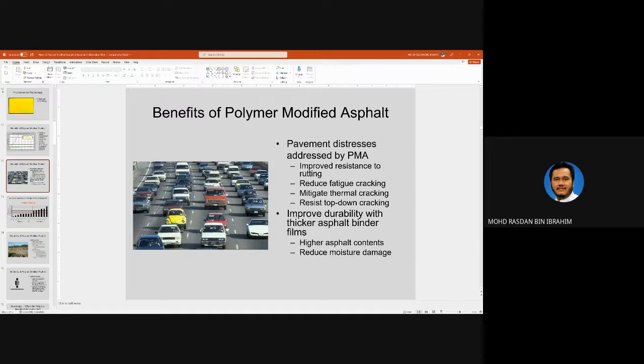And then improve durability with thicker asphalt binder film. When you modify the bitumen with polymer, the viscosity of the bitumen will increase, and when it increases, the asphalt film that coats the aggregate is going to be thicker. Recall at the beginning of last lecture, I have explained to you how thicker asphalt binder film will affect the optimum binder content of a pavement. So subsequently, when you have a thicker asphalt film, you would need a higher asphalt content because you need a lot more bitumen, and also thicker asphalt binder film will actually reduce moisture damage because it is more difficult for moisture to get into the aggregates.